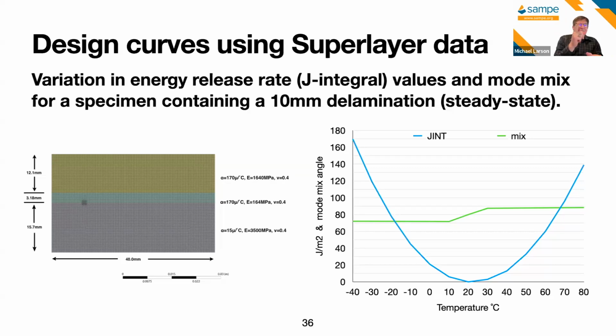your specimen. And the curve on the right is the design curve that goes along with that. You do have that shift of the mode mix, whether you're on the hot side of things or the cold side, where we get that jump from a more balanced shear and opening to the driving shear dominating things. But the blue line shows the J value at different temperatures. So once you're in an oven, you can identify what the critical value is for where the failure occurs. And then you can get a sense of, for temperatures less than that, how close you are, what kind of factor of safety you are dealing with within the bounds that cause failure to occur.